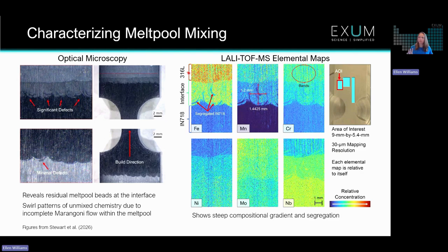And if we look at the iron map, we can very clearly see we've got this area that's purely 316L, we've got high iron, we've got this area with low iron, that's the Inconel 718, but this interface area is an area of mixed chemistry, where you see a very steep gradient on the iron map compared to less of a steep gradient on the nickel map, as we're changing from nickel to stainless steel. And again, you see that segregation or those swirl patterns where we have low iron, we have low manganese, we have low chromium. So essentially we have low amounts of all of those major elements that are in the 316L.